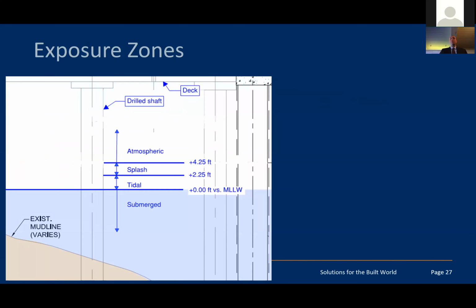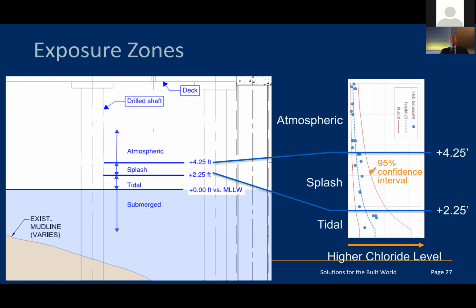We also defined different regions, exposure zones, on the drilled shaft. So we have zones that are submerged, tidal, splash, and atmospheric. And you can see how the chloride profile levels varied with the exposure zone. So in that tidal and splash zone, we expect to see the highest, which is what the data indicated as well.